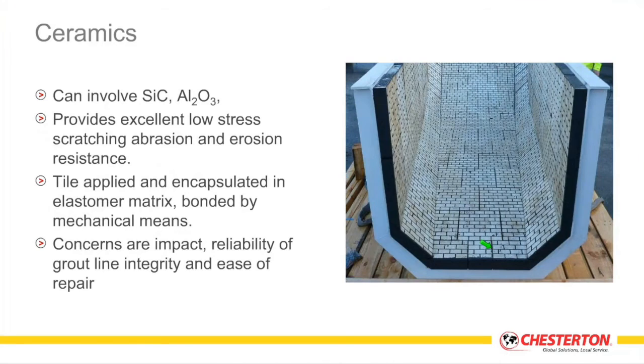And then you can see situations where ceramics are being used. Now, ceramics typically involve either silicon carbide or aluminum oxide based materials. These are chosen because they have excellent resistance to low stress scratching abrasion and erosion corrosion. These materials are inert materials. They are typically applied in a glue fashion. Sometimes they may be encapsulated into a rubber matrix and mechanically attached onto the surface. But this is a sacrificial wear coating that is intended to resist sliding, low angle of impact wear.